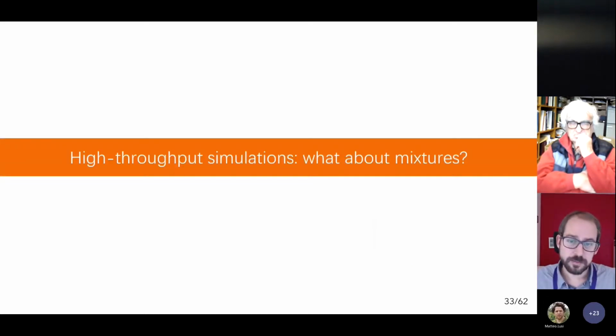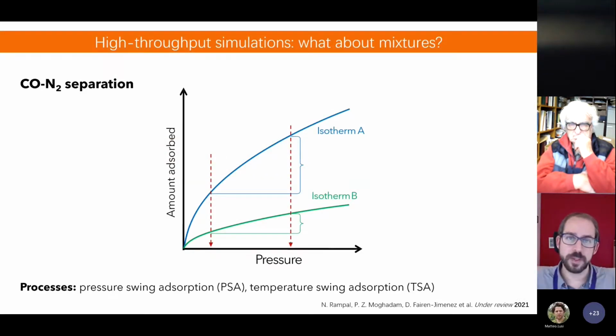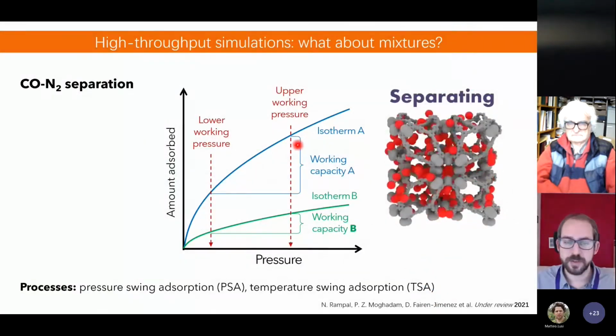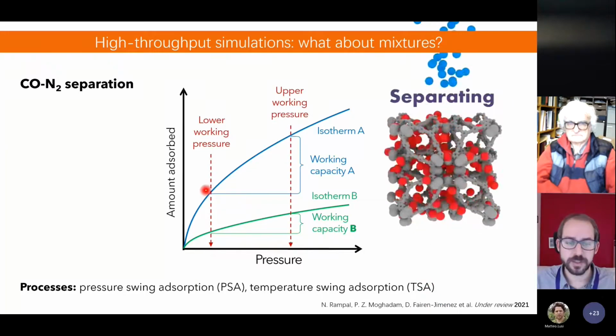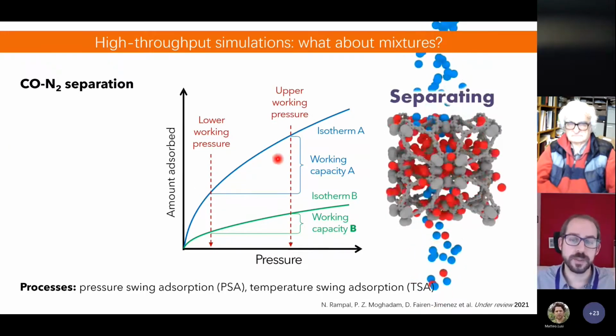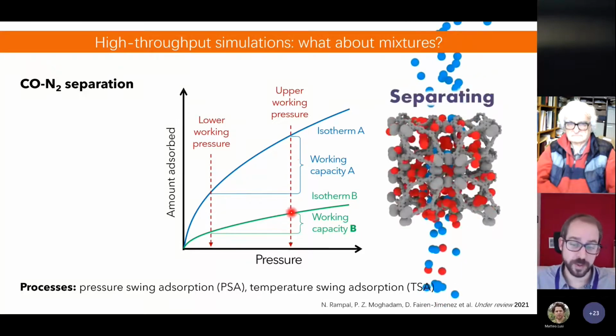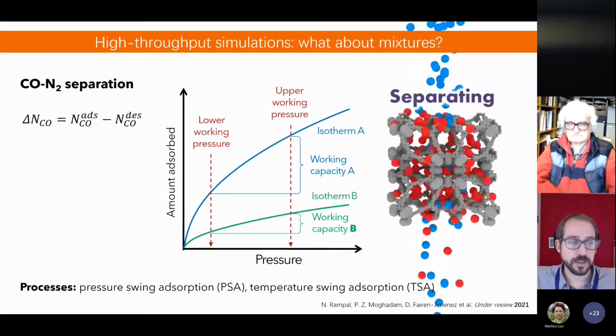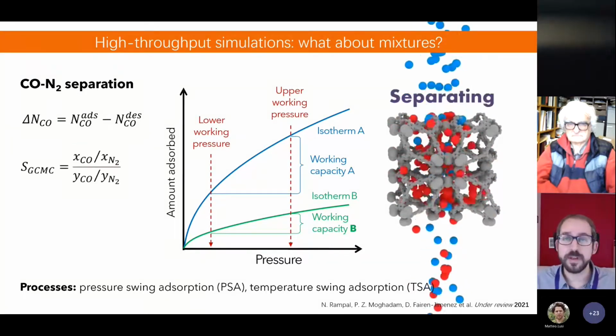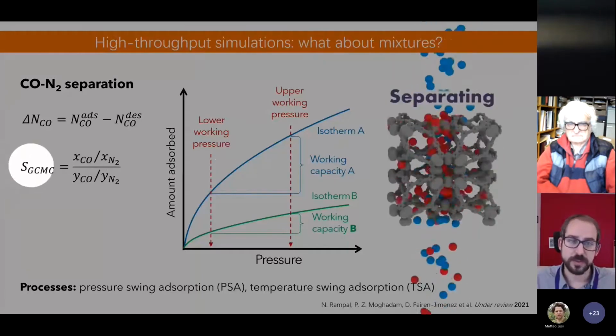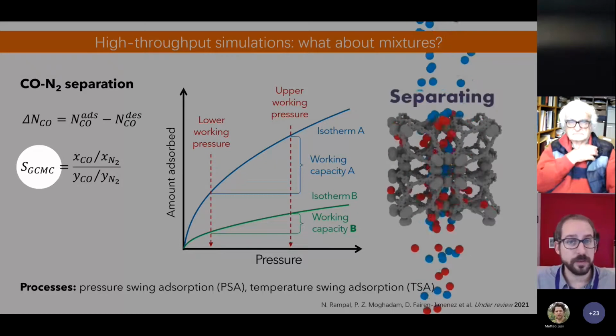This is for single components, basically the amount of hydrogen we can really store, or if you want, the working capacity. But when we are having mixtures, the situation is a little bit more complex. We need to pay attention to different parameters. We need to pay attention to these working capacities that I'm describing here. This is basically the difference of the amount of gas that is adsorbed at high pressure minus the amount of gas that is adsorbed at low pressure. And depending on the shape of the isotherm, this working capacity is going to be higher or lower. This is quite important. As I said, this is the working capacity, but then we have other parameters that are also going to be extremely important for mixtures. In particular, the selectivity of a structure is going to be really, really important.